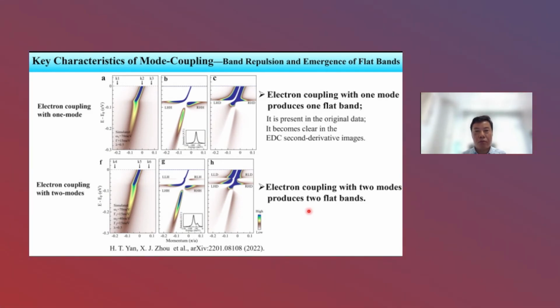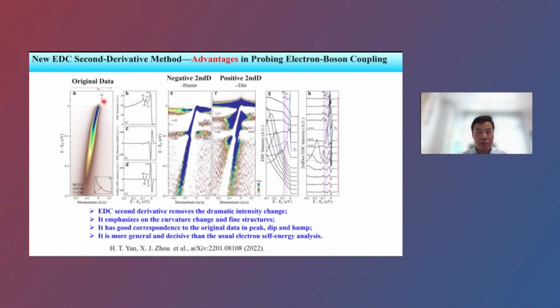So that's why when we come to the real data, like this data we take along the node direction, if we do the second derivative, you can really see these two flat bands here. So this is very consistent with the simulation.